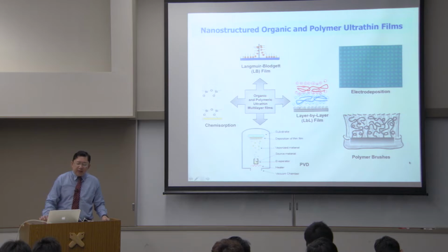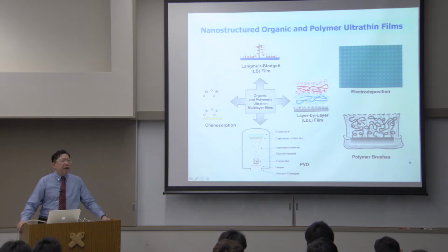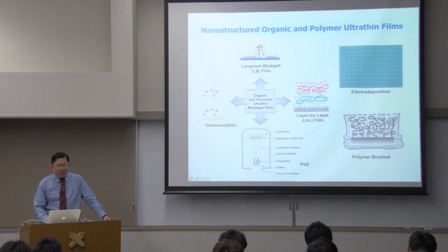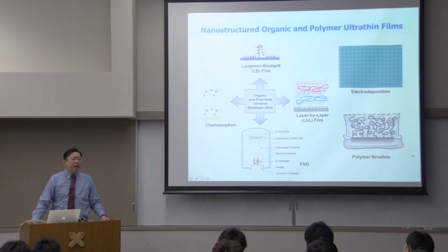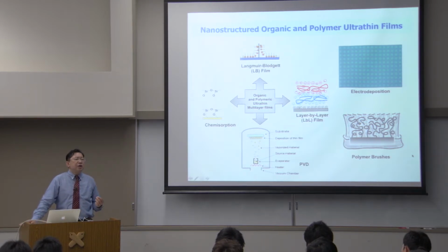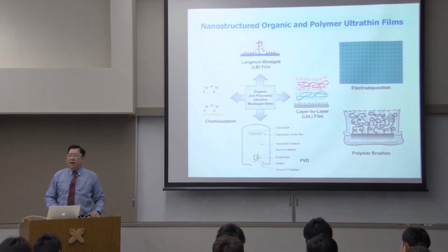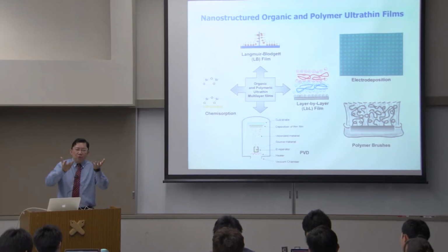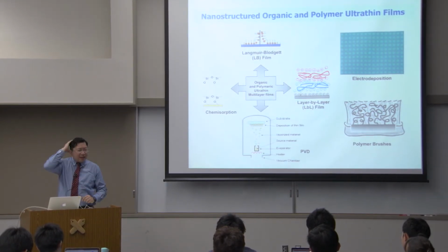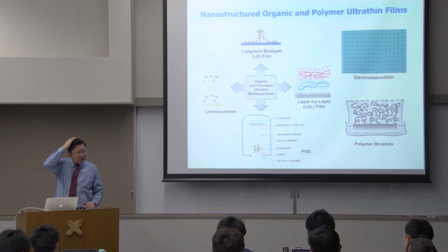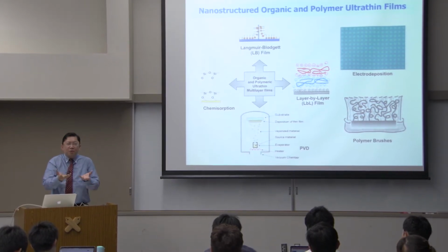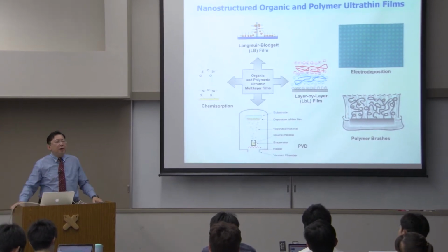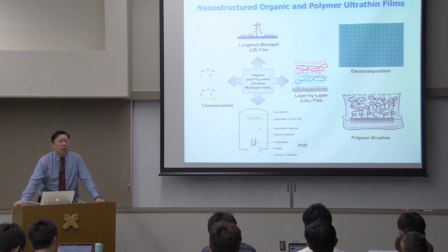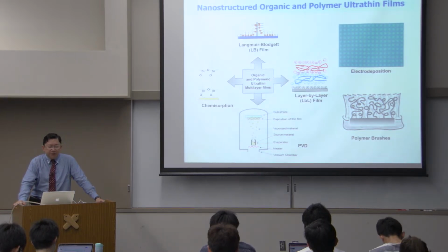The other technique that we did a lot, and many other groups, is in the area of polymer brushes or polymer grafting. Polymer brushes means that we can prepare initiators on surfaces and then cause the polymer to grow from the surface, just like hair. Hair comes from your head, so you can make polymer grow from the surface. That's called grafting from approach in polymer brushes.